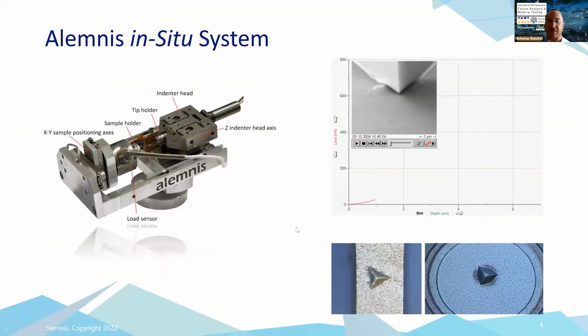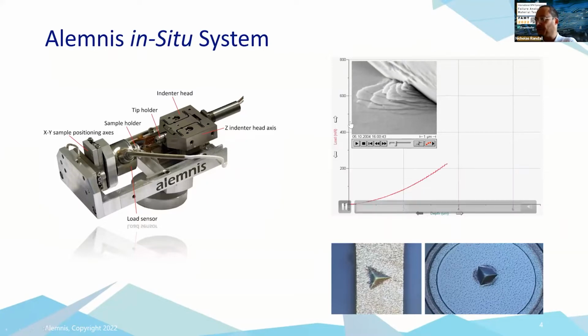So what is an in-situ test? You can see it here. This is an indentation into a bulk metallic glass, actually. The load displacement curve doesn't necessarily tell us what's happening at the interface, whereas being able to see the test live with the SEM shows us that we actually have some slip planes here.